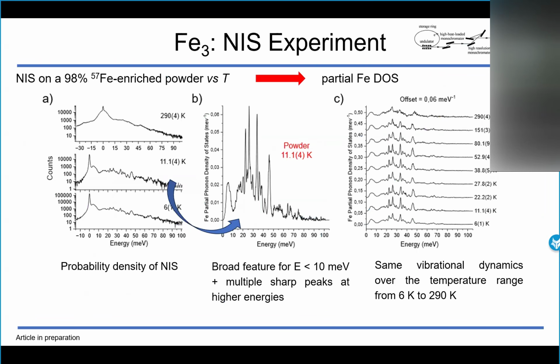And then we can see the nuclear inelastic scattering data. First of all, data from the powder. At the left, you can see some nuclear inelastic scattering data at different temperatures, showing the elastic peak plus sidebands. At the center, you can see the partial phonon density of states that we have calculated at 11 Kelvin. You can see that we have a broad feature under 10 millielectron-volts, and then multiple sharp peaks at higher energies. We repeated this measurement at various temperatures between room temperature and 6 Kelvin. The spectrum remains practically the same, indicating that the vibrational dynamics is practically the same in this thermal range.